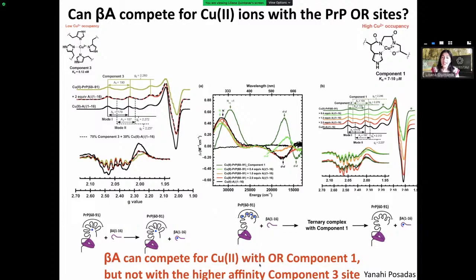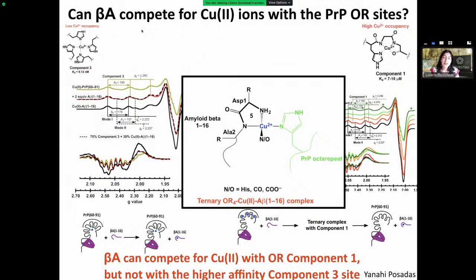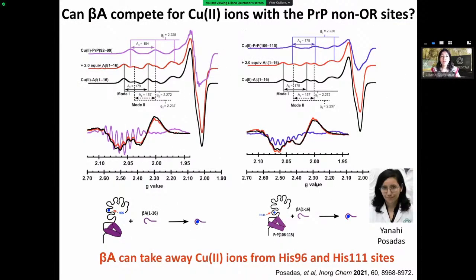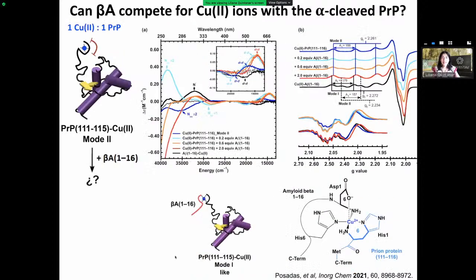However, at intermediate points of the titration, she could see evidence of a ternary complex being formed. So at some point in the titration, we can see species like this one, copper bound to the histidine of the prion protein, but also bound to the amyloid beta peptide, so ternary complexes. In the non-octa repeat sites, the story was much easier. In both cases, the amyloid beta peptide wins, so it can really take away the copper from these sites. And in the alpha-cleaved prion protein, because of the nature of this peptide, we actually end up with ternary complexes.